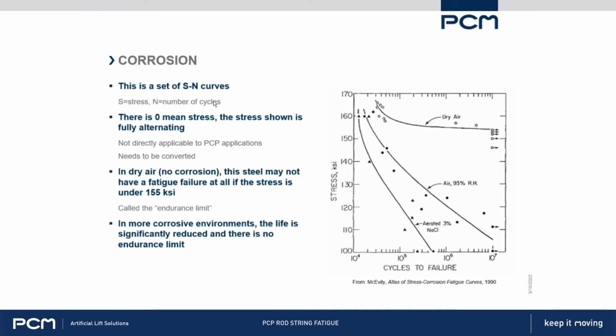So just for corrosion here, I want to talk about this a little bit. This is a set of SN curves for a particular material, and they've done 3 tests here. The first test was in dry air. You can see the basic shape of the SN curve based on the dots they've got. These ones over here, these lower stresses, they never failed.